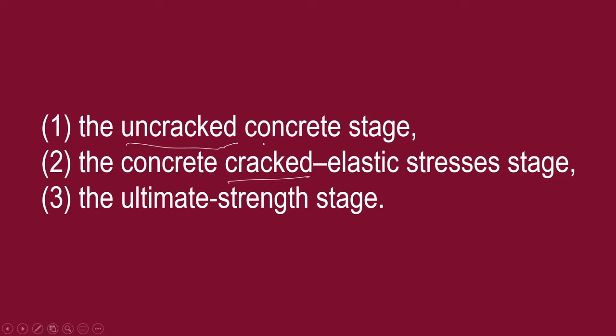2015. Maybe they will give a problem using the NSCP 2010. The modulus of rupture using the NSCP 2010 is 0.7 lambda times the square root of fc prime. You should memorize this. So the modulus of rupture is equal to 0.62 lambda square root of fc prime for 2015. For 2010, that is 0.7 lambda square root of fc prime. Memorize it. Okay, let me erase this one.